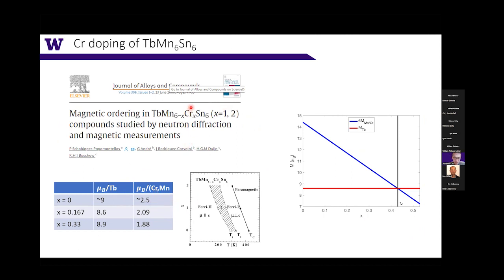So for example, in this work that was also done quite a while ago, they used neutron to study this chromium substituted terbium manganese six tin six with 2 dopings. And then what they found is that the terbium moment doesn't change much. It's still around 8.5 to 9, but the average moment of the chromium manganese is much reduced. And then the spin reorientation temperature and the critical temperature of the ferromagnetism are also reduced.